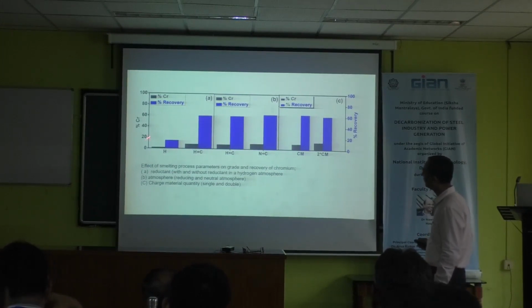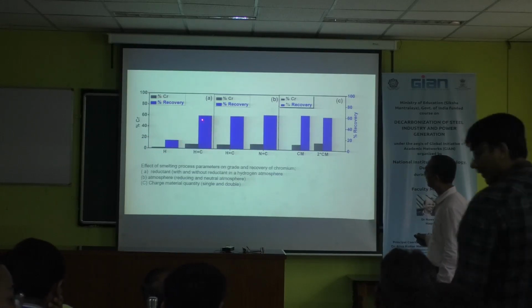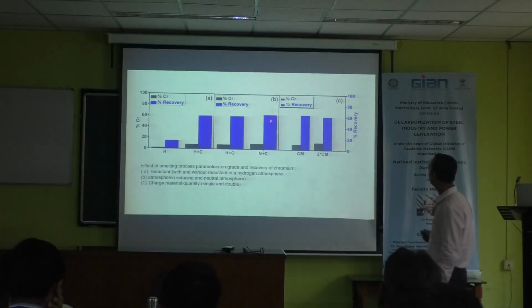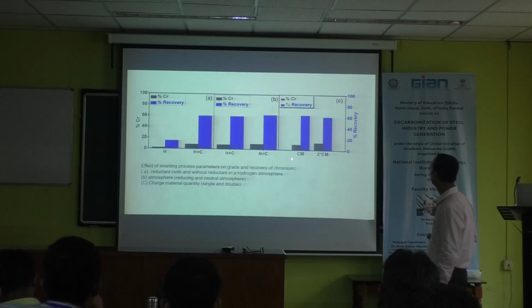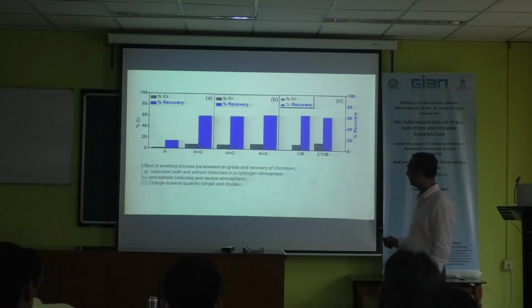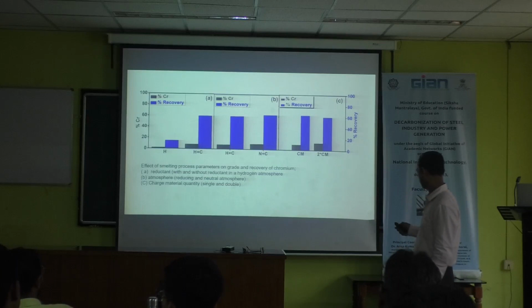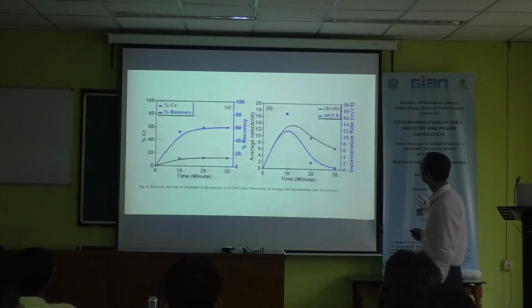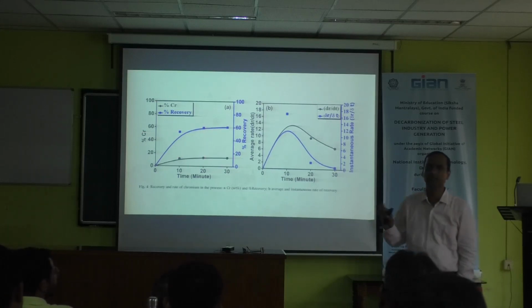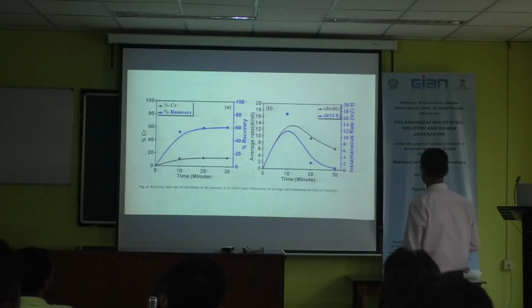So if you see only hydrogen plasma, the reduction recovery is less. But with the addition of stoichiometric carbon, and double stoichiometric carbon, in the next slide you can see the recovery is almost 60%. With time, up to 20 minutes of exposure, you can get the maximum recovery.